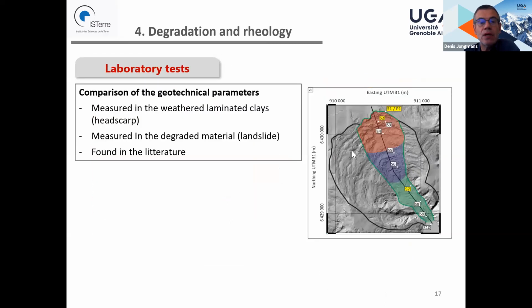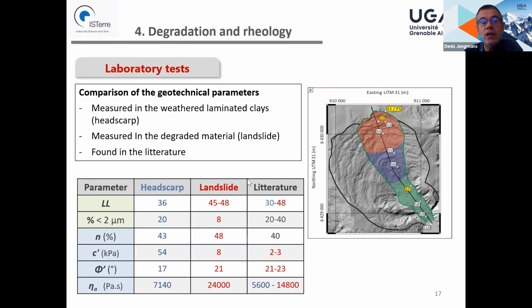at this site. So we also performed some laboratory tests. And as you have noticed, we performed a very small number of tests, 2 and 3 for the mechanical tests. We measured the characteristics in the weathered laminated clays at the escarp and in the degraded material inside the landslides. And we compared these results to the ones found in the literature. So here I summarize the main results of the geotechnical tests with the different parameters at the escarp, in the landslide, and compare with the literature.